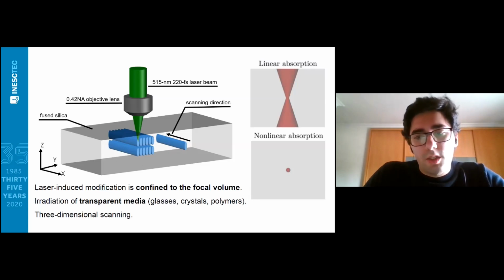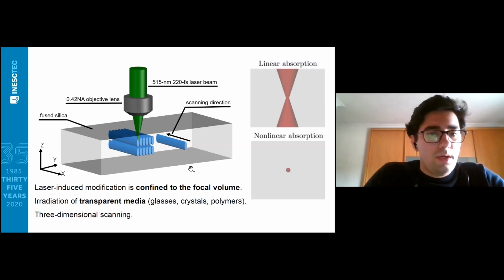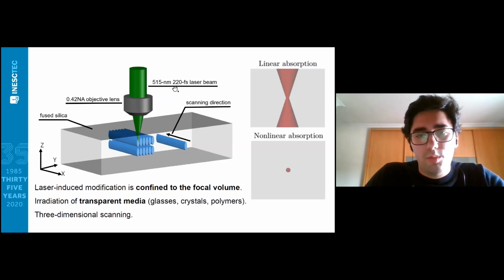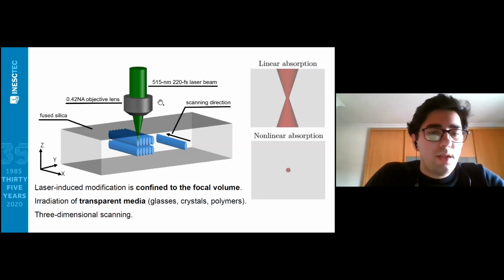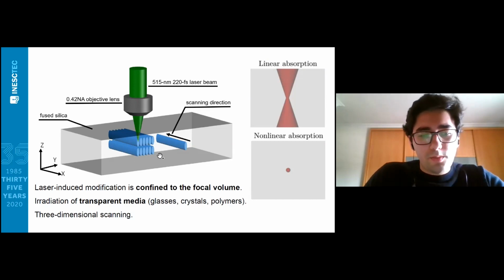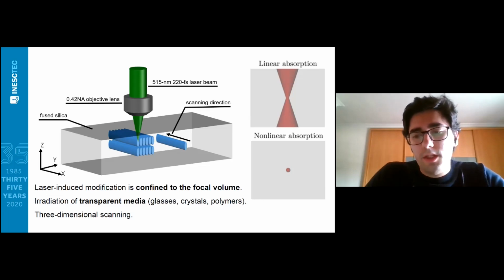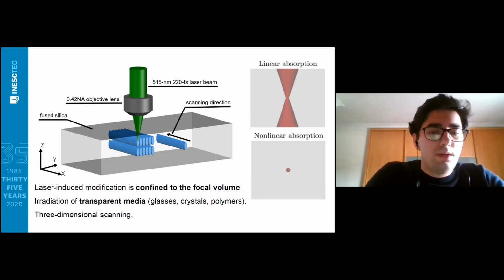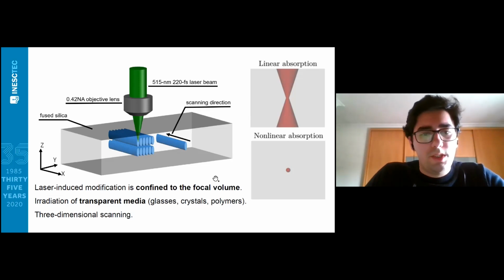However, to have these types of processes, you need high peak intensity. That's why you need to use an ultra short pulse beam. Here we use a beam with a pulse duration of 220 femtoseconds, and that is also why the beam has to be tightly focused within the sample. The importance of nonlinear absorption, as I said, is that it will confine the laser-induced modification only to the focal volume, and so this way we can fabricate structures with micrometric precision.